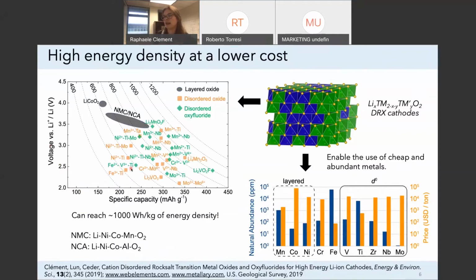As you can see, compared to state-of-the-art commercial cathodes, some of our disordered rocksalt compounds are performing very well. And so some of these materials have energy densities up to 1,000 watt-hour per kilogram at this point. And it's a relatively recent field, so performance improvements are likely to occur.